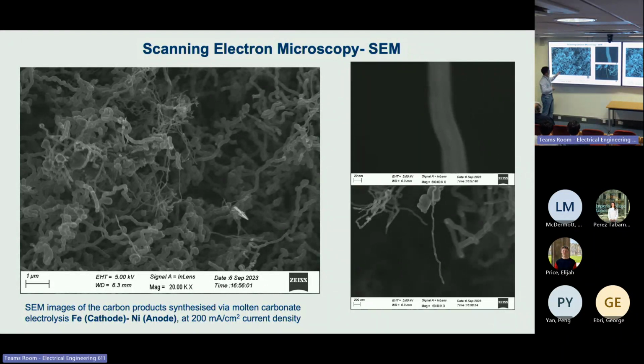We can see some thin fibers here, and also a thick tube there. And we also observe some carbon nanoparticles. The diameter is around 50 nanometers, compared with the 20 nanometers diameter of the CVD synthesized carbon nanotubes.